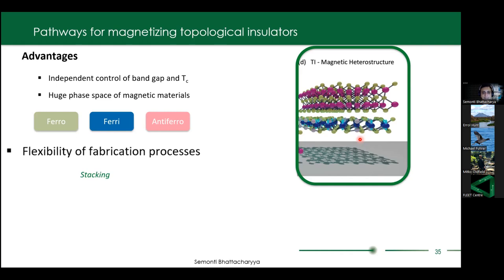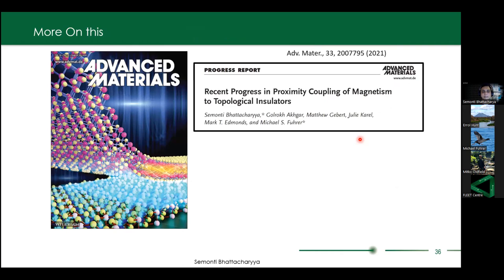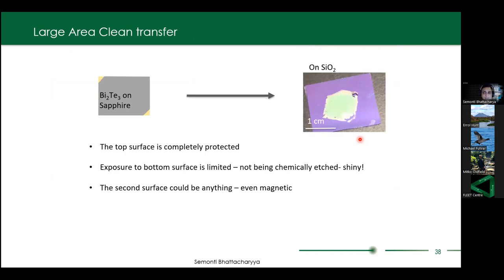Topological insulator–magnetic insulator heterostructures are quite promising because you can tune the properties of the topological insulator and the magnetic insulator separately, then place them on top of each other and let proximity-induced magnetic coupling take care of the magnetization. The advantage is that the band gap of the topological insulator and the Curie temperature of the magnetic insulator can be chosen independently, and there is a huge space of magnetic materials available — including ferrimagnetic or antiferromagnetic materials. This also gives flexibility in fabrication, using van der Waals stacking. We wrote a review paper on this topic during COVID when experimental progress was limited.